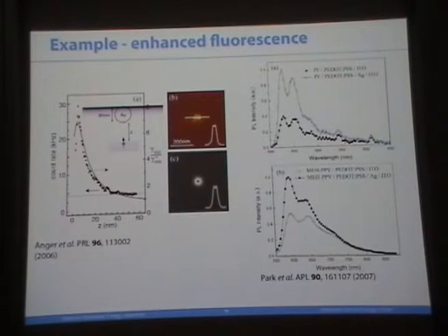Another example, and this starts going into the more relevant area for organic photovoltaics. Here we have a dye that is separated by a certain distance from a gold nanoparticle, and we look at the emission rate from that dye. This is basically just the fluorescence intensity, and you can see there is a factor of 6 or more enhancement in the fluorescence intensity of that dye. Then if you move the particle away, which is done by a spacer sitting in between, the rate goes down, and that follows this relationship that they calculated very nicely. Also, if you get very close to the metal particle, another effect occurs in which you actually lose fluorescence intensity, because of energy transfer to the particle, so you actually lose energy. That's something to be mindful of.